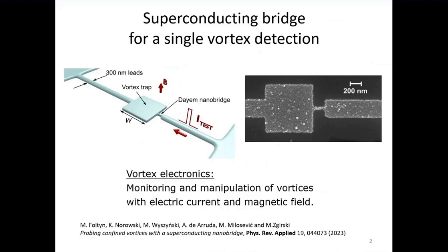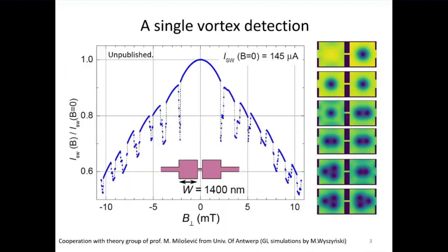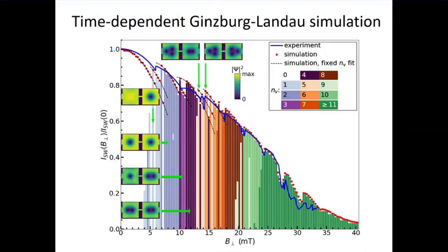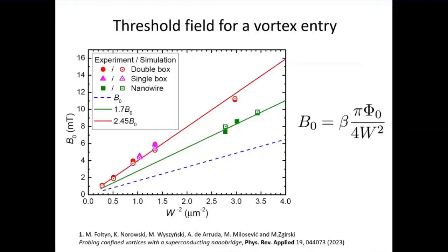Although the global temperature of the fridge is, say, 300 millikelvin, you can overheat in nanoseconds to 2 or 5 K easily. Then when it cools down, since the magnetic field is on, it is field cooling and the vortex is spontaneously trapped. You can find this calibration curve in this paper also.